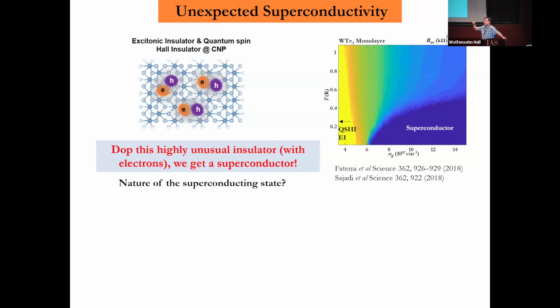You say like superconductor, you observe 1, 2, 3, confirm it. But what we do is we really rule out, for example, a simple band structure insulator by doing density-tuned tunneling spectrum. There's also Hall effect. There's a whole paper there. So there's a bunch of experimental evidence and also theory to allow us to say that we really do not know anything else except excitonic insulator. So it's a very strong case of excitonic insulator.